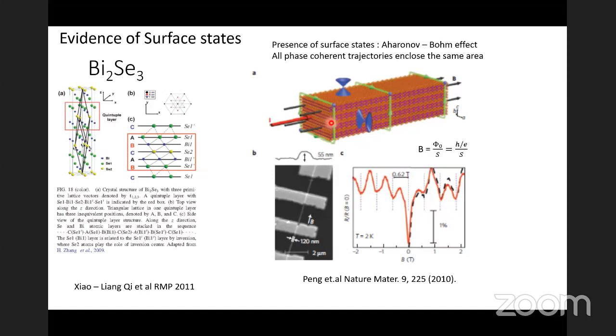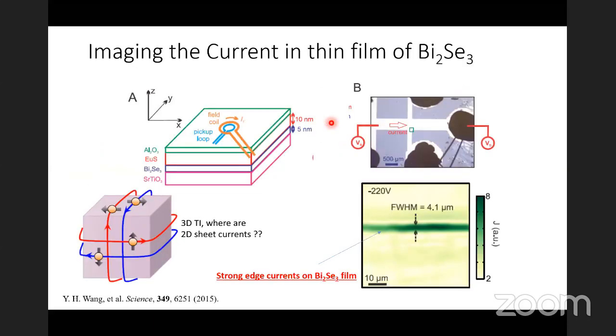There are other experiments which also establish the presence of these conducting surface states and a bulk gap state inside the 3D topological insulator. But then people wanted to look at the distribution of these currents on the surface. 3D topological insulators should have this sheet of 2D currents distributed on the surface. So people used scanning Hall magnetometry, or scanning SQUID magnetometry, to look at the distribution of these currents. Here you have a Bi2Se3 film, and you do scanning Hall over the entire surface and see the current distribution, because the current generates a magnetic field, and that magnetic field is picked up by the pickup coils of the SQUID loop.